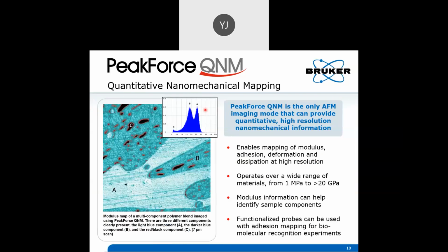You can also do imaging. So here, if you see this image, I can see there are 3 different phases, the really light blue, the slightly darker one, and the black one, but you do not know which is what. Then when you do the modulus mapping, you can clearly see that C is the softest material at a few megapascals, and A and B are much harder at a few gigapascals, right? So this ability to pinpoint which material is where based on mechanical property is really powerful, especially these days, when most materials in material science have complex chemistry and complex composition. So it's a very powerful technique.